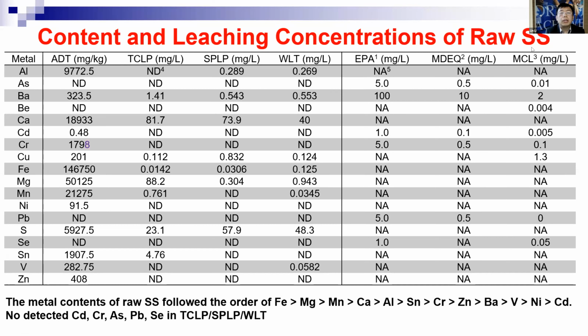Because this table has many data, basically the information we want to take from here is the metal contents. In terms of content, the iron that is most in there is the highest, and cadmium is the least. Even we have some... no, this cadmium is here. So this one, I guess I have a typo here. It should be no chromium, arsenic. So this is just to say TCLP didn't test that. Cannot detect, below detection limits.